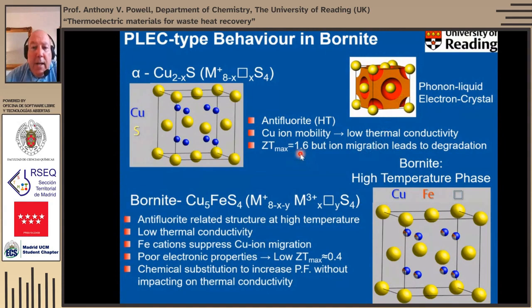However, ironically, it's that ion migration that leads to these materials degrading in use, because if they're subjected to a temperature gradient and have liquid mobile copper ions, and there's also a potential difference being generated, you'll get copper ion migration, and it's seen that copper starts to plate out on one face of the thermal elements under sustained operation. And of course, then the performance degrades. So what we wanted to do is try to stop that migration. So we looked at this material bornite, which is a high temperature phase, also anti-fluorite related.